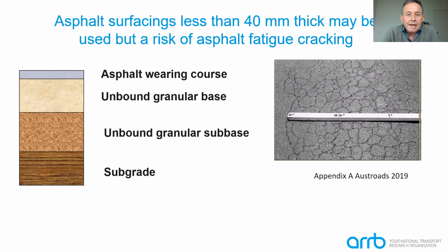But what we do say is that if you do that, there is a risk that you'll get fatigue cracking of the asphalt, limiting your life. So it's a risk that the designers need to consider when they adopt this sort of pavement configuration with a thin asphalt surfacing. There is a risk that you will actually get fatigue cracking, and the surfacing will need to be removed and replaced prematurely. You might have designed the granular pavements for 20 years, but you might have to remove and replace this thin asphalt wearing course 5 to 10 years after opening to traffic.